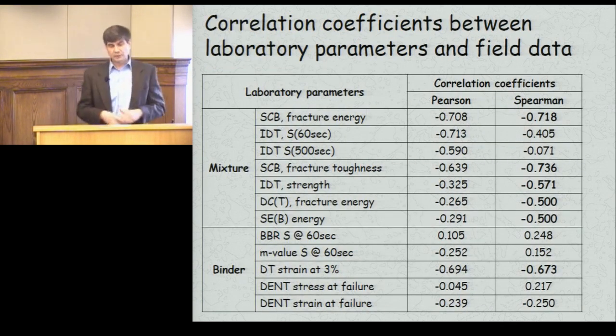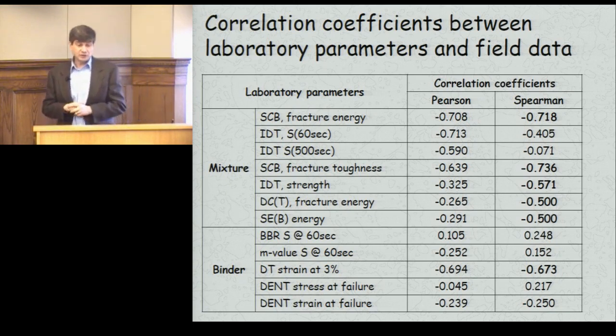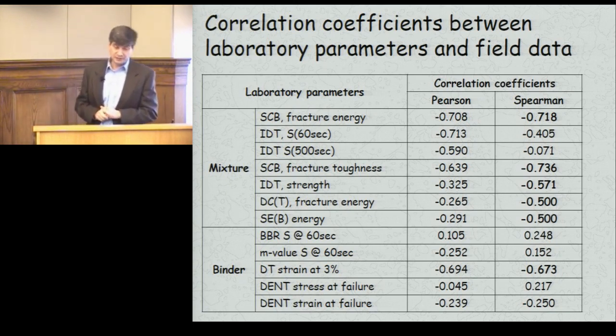And we got the results, and then we actually did simple correlations. We found out that for mixtures, the highest correlation with the occurrence of thermal cracking was observed for fracture type tests, fracture energy, both the SENB and DCT, and also fracture toughness. For asphalt binders, as I mentioned, the strain at failure with the direct tension.